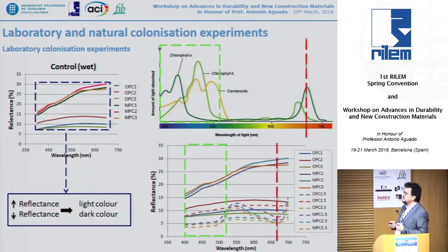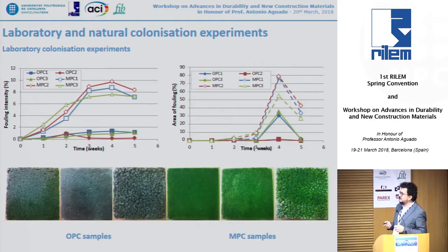So these are part of the results in order to show how we measure the colonization by controlling the wavelength according to the presence of chlorophyll. We used green algae, so we can control very easily this increase in the absorption of the green light. So these are the raw results, but these are the treated results in order to see how the fouling intensity, the area of fouling, changed with the duration of the test.